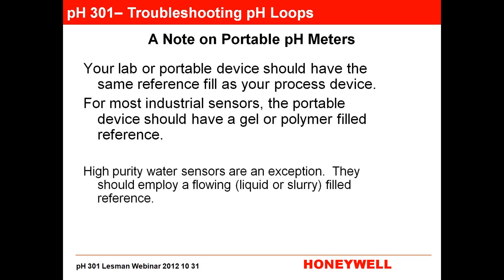If you're in a high purity situation, then you are using a high purity pH sensor, which requires a liquid potassium chloride that is being fed through a reservoir into your flow cell. And then in that case, you would want a portable pH sensor that has a flowing reference or liquid or slurry inside. And you can almost always look at portable pH sensors. They're either plastic tubes or glass tubes, and you can shake them around and see what's inside there in the main tube.